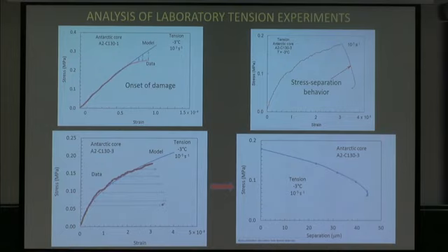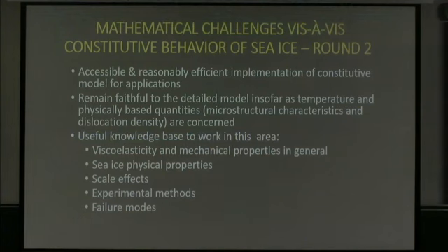This test here was spectacular because it actually captured a few load points as the crack was propagating. So this gives what's called a stress separation curve, which is very unusual in lab experiments. By the same token, looking at the model, we can tell that the behavior is all explainable with elastic and anelastic behavior up until the point that the crack started propagating. And then we can actually quantify that stress separation. This is one of the key parameters that the fracture mechanicians need for their kind of analyses.